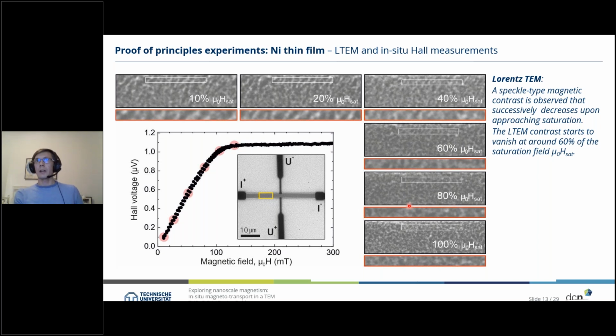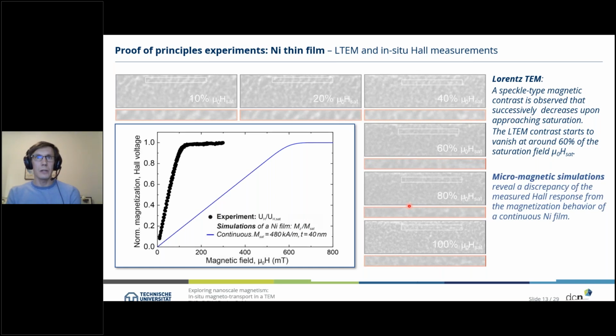So we thought, okay, how can we understand that? Let's start to simulate the system using micromagnetic simulation. And since nickel is a well-known material, we can directly put in the material parameters like the saturation magnetization and the film thickness. And what we found is that the simulation of a continuous nickel film seems to be completely off when we compare the Hall voltage of our measured film to the simulation. And that was quite surprising.